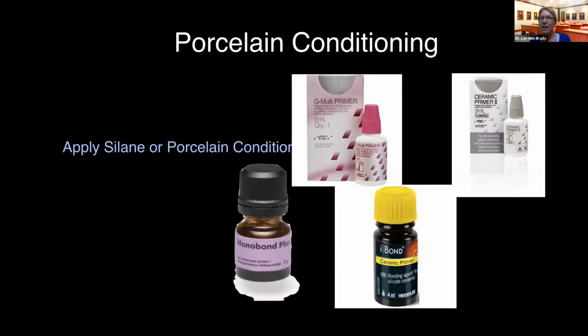So I was told by my lab that Monobond Plus is not needed after using IvoClean for zirconia. It depends, are you bonding or cementing? If you're cementing, if you're gonna clean with IvoClean and then go to a glass ionomer material, you don't need Monobond Plus. If you're gonna clean with IvoClean and go to a cement and you've got mechanical retention, you don't need Monobond Plus. If you're telling me you're trying to bond that zirconia, you've gotta put some sort of a primer on that zirconia, something that contains MDP. So depends on what your process is.